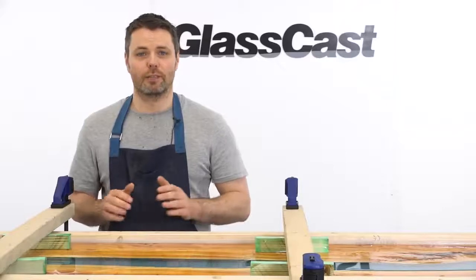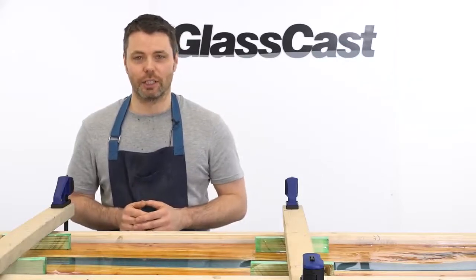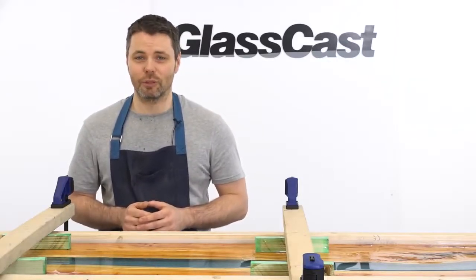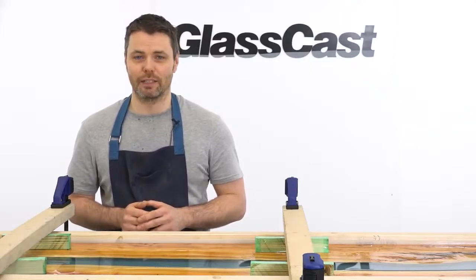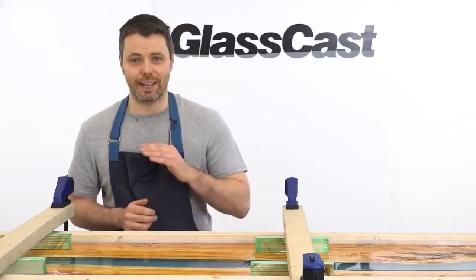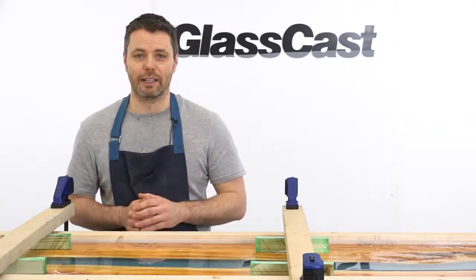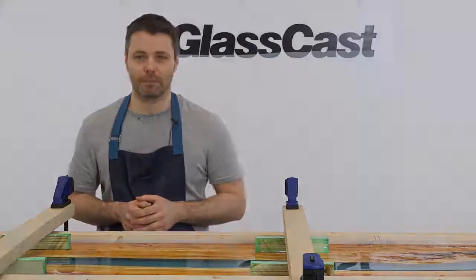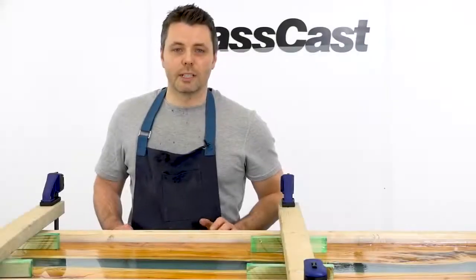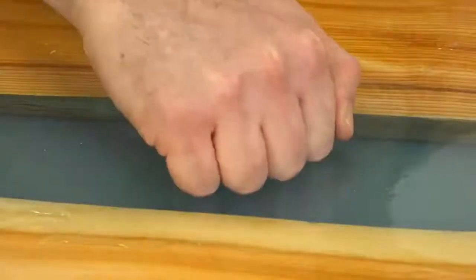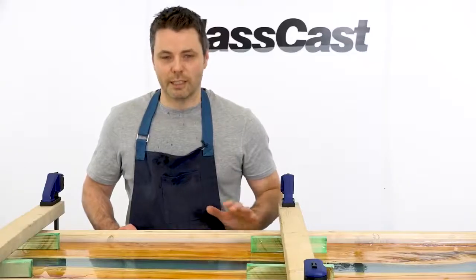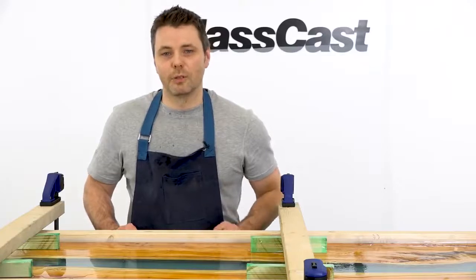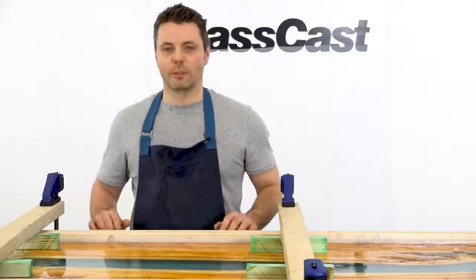With the final pour now finished, we just need to leave the resin to fully cure. This will take at least 48 hours at 20 degrees, and it's really important in that time to maintain the temperature throughout and keep dirt and dust away from the surface. It's a couple of days later now, and as you can see, the Glass Cast 50 has cured to a really hard finish. That means we can now move on to the final stages of finishing this table.